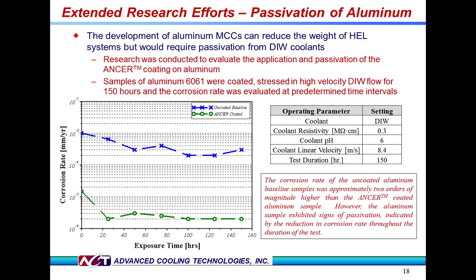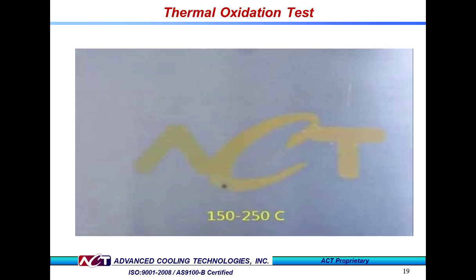We have only 150 hours of life data, but these early results are encouraging. Like we saw in the initial copper testing, ANCER-coated samples, seen as the green circle, have approximately 2 orders of magnitude lower corrosion rate than the bare 6061 aluminum sample. Again, we'll just have to wait and see, but these preliminary results are promising.